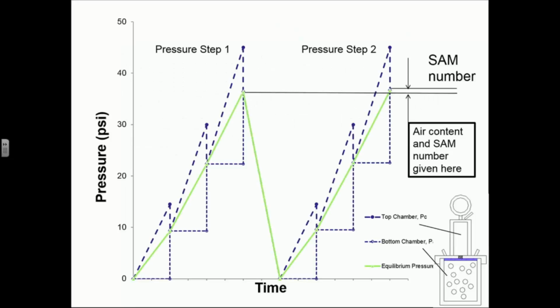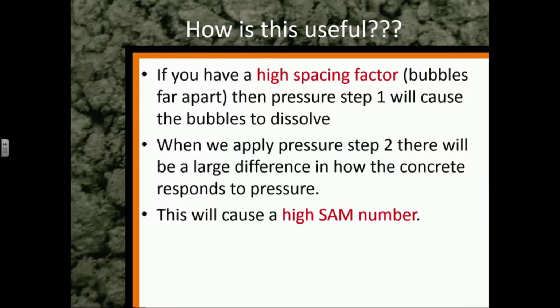So I'm going to talk about this. I'm trying to get really practical for a second on why we do the test the way we do it. Pressure step number 1 is our first pressure cycle. Pressure step number 2 is our second pressure cycle. And remember, I told you earlier, we compare the two pressure cycles to determine the quality of the air void system inside our concrete, or the SAM number. If you have a high spacing factor, bubbles far apart, then when pressure step number 1 happens, it's going to cause your bubbles to dissolve. Then, when we apply pressure step number 2, when you punch it the second time, there's going to be a large difference in how the concrete responds to pressure. That's important. Big difference between pressure step number 1 and number 2, because the bubbles dissolve, so the bubbles are not there anymore. When you go to push on them the second time with pressure step number 2, that will cause you to have a high SAM number.